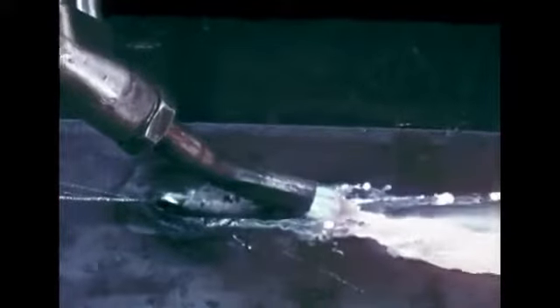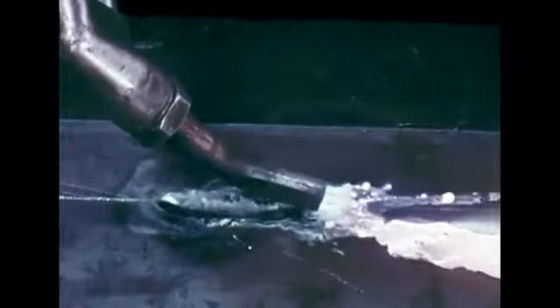The nozzle angle is important. If it is much more than 30 degrees, slag tends to flow backward into the groove. If the angle is much less than 7 degrees, the groove becomes so shallow that the cut is soon lost.